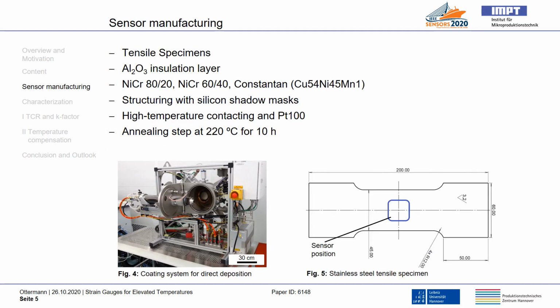The sensor manufacturing takes place with a new coating system for direct deposition based on a sputtering process, as shown in Figure 4. It consists of a process chamber, which will be closed by the substrate itself for the vacuum process. That's the reason why it enables the deposition of components of arbitrary size. For our investigations, we chose stainless steel tensile specimens, as shown in Figure 5.